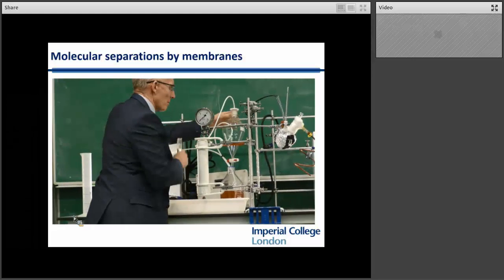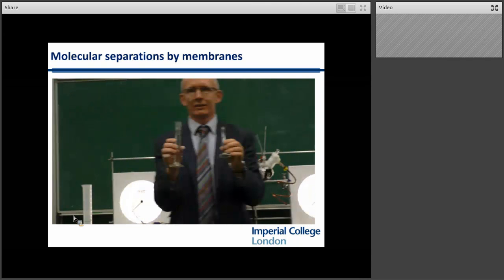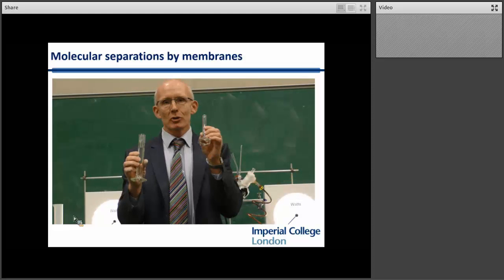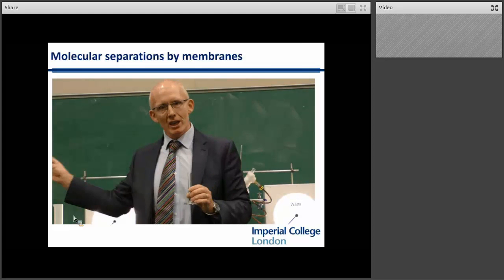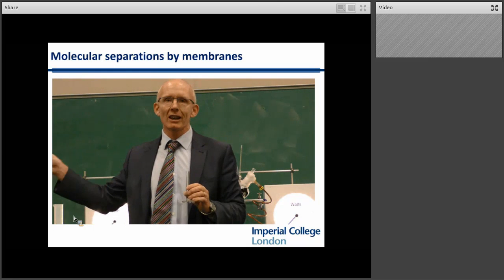And in the membrane experiment, I've generated over 50 mils of water. So what a comparison. Here, cycling for a minute at 250 watts, wearing myself out, I've produced 2 mils of water. Here, cycling for a minute, running at only 50 watts, very sedately, I've produced over 50 mils of water. And that is why membrane technology is far more effective than thermal techniques for purifying water.